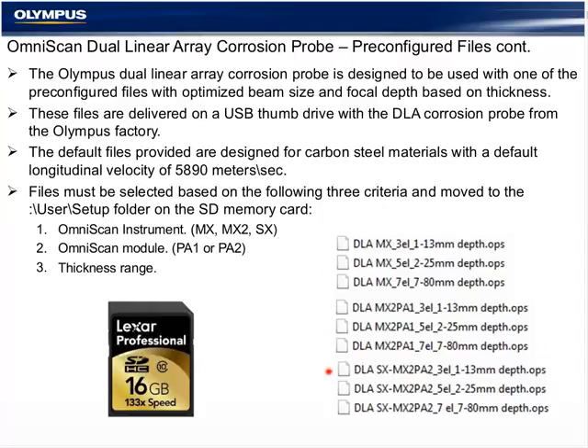The thickness range is a modification in the wedge delay and setup of the gate position and color palette relative for three ranges, of which the overwhelming majority of the thicknesses for corrosion mapping that we see at Olympus would be the 2 millimeter to 25 millimeter depth here.